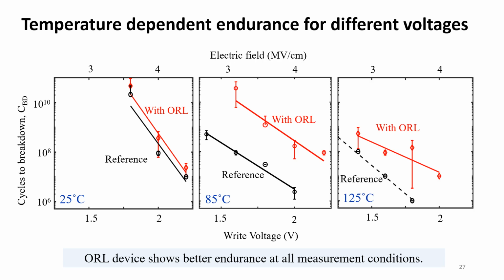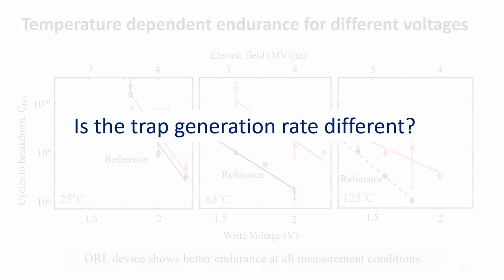And this difference is even higher at 85 and 125 degrees. So the endurance of the ORL device is much higher compared to the reference device at 85 and 125 degrees Celsius. So next we wanted to understand where this endurance enhancement is coming from, and if trap generation rate is playing a role here.